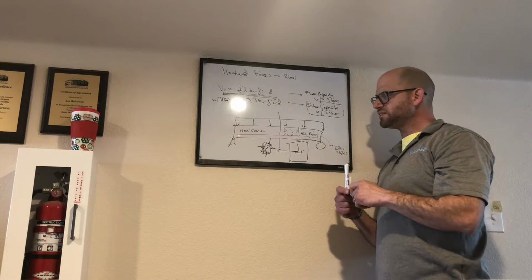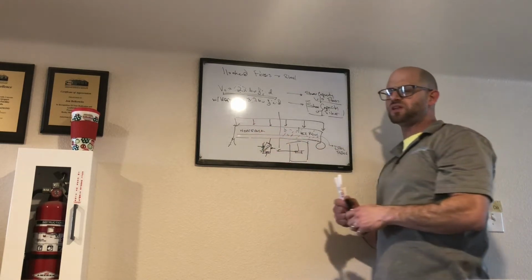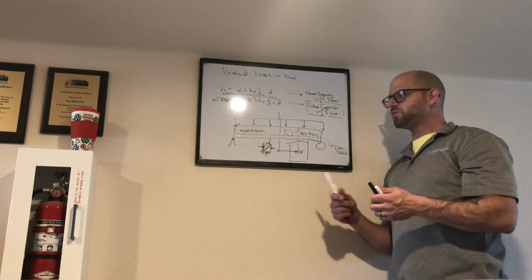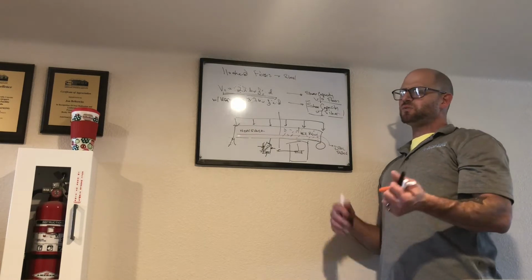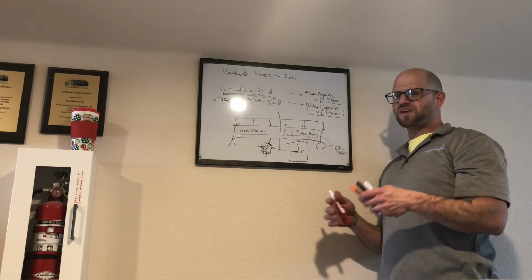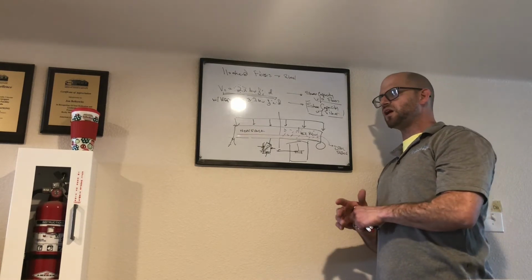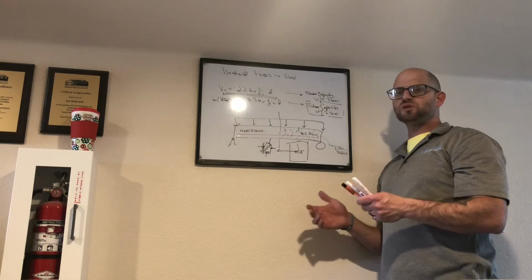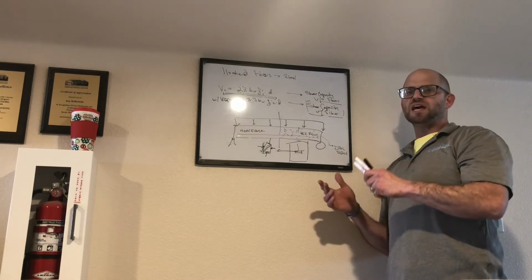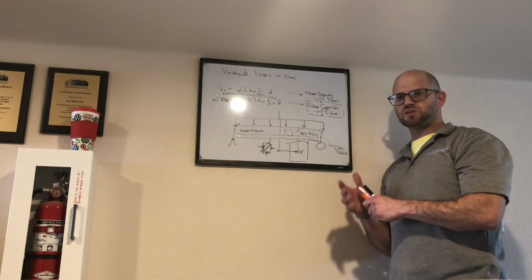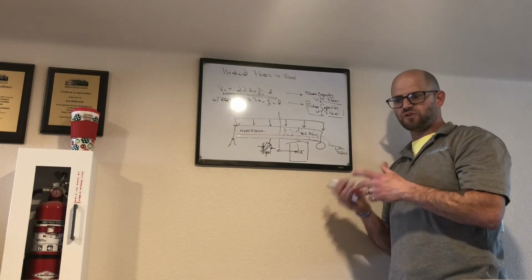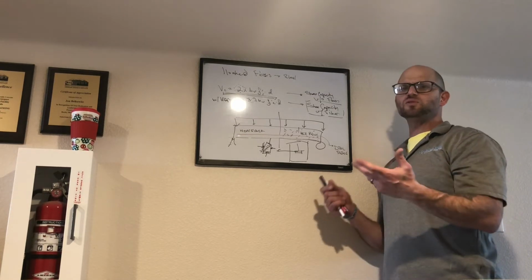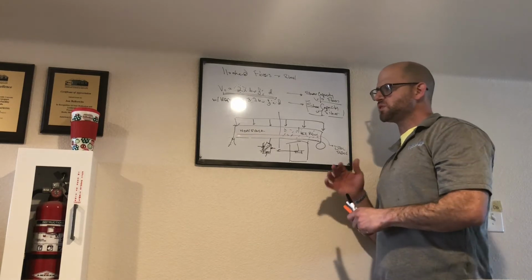So that's really why we're seeing an increase. With hooked-end fibers, you can use them anywhere between 0.5% all the way up to crazy amounts like 3 or 5% in a cubic yard of concrete. In doing so, you always have to take into account that the amount of fibers you're going to use will have an effect on the fresh properties of your concrete, and that goes to mix design, but that wasn't the purpose of this presentation today.